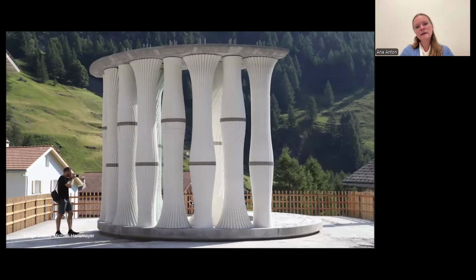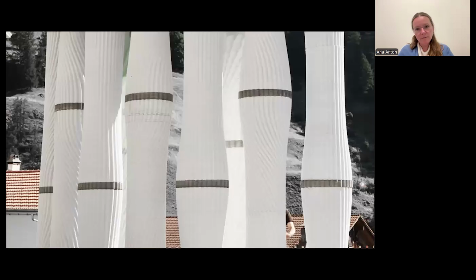We tried here to use between the segmented elements prefabricated concrete sleeves to account for the imperfections of the layer. However, this was not 100% successful, and we came up with a different strategy for the final tower. And you can still see that the process had imperfections by how the elements were printed.